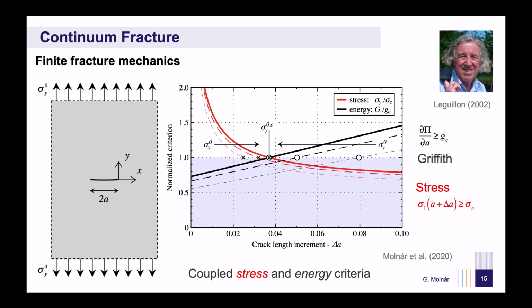The coupled criterion states that a crack can initiate and propagate only when both stress (strength) and energy-based conditions are satisfied. For example, in mode 1 tensile opening, if the applied load is low, a longer crack is required to dissipate the necessary energy to create a new fracture surface. However, the crack does not propagate because the stress remains below the material's strength. As we increase the load, we eventually reach a point where both conditions are simultaneously satisfied. And this defines a finite crack length.